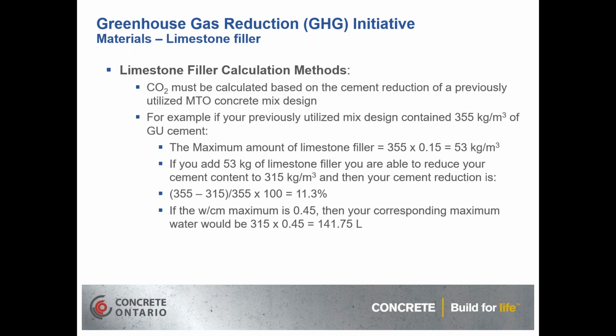So, the carbon dioxide reduction must be calculated based on the cement reduction of a previously utilized MTO concrete mix design. So, for example, if your previous mix design was a standard old school city sidewalk mix with 355 kg per meter cubed of type GU cement, the maximum amount of limestone filler that you could have in your concrete would be equal to those 355 kilograms per meter cubed times 0.15, because we're limited to a maximum of 15% of the cement mass. And that gives us a maximum amount in the mix of 53 kilograms per meter cubed.